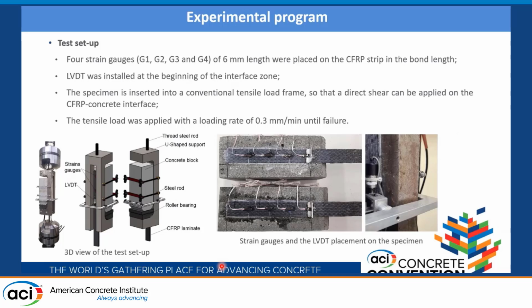After freeze-thaw cycling, each sample was instrumented with 4 strain gauges placed on the CFRP strip along the bond length. In addition, an LVDT was installed at the beginning of the bond length to record the slip of the joint during testing. The specimen was inserted into a conventional tensile load frame so that direct shear can be applied on the CFRP concrete interface. Then each specimen was tested in tension to failure at a load rate of 0.3 millimeters per minute.